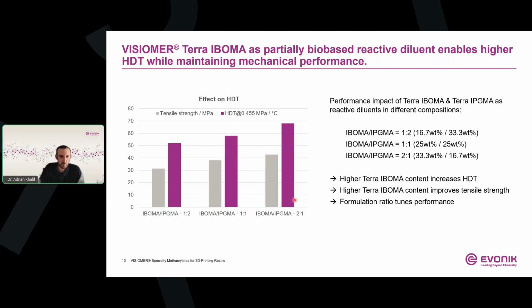At the same time, we do not observe a trade-off in mechanical properties. In fact, we see also that the tensile strength increases with the increasing IBOMA content, because the final Tg of the polymer also increases. So this demonstrates also an important principle. By adjusting the ratio of the Terra IBOMA and the Terra IPGMA, formulators can tailor the balance between not only the handling properties and the sustainability benefits, but also the thermal mechanical performance. So in this specific case, the Terra IPGMA and Terra IBOMA can be viewed as complementary building blocks that allow resin designers to tune their performance according to the application requirements.